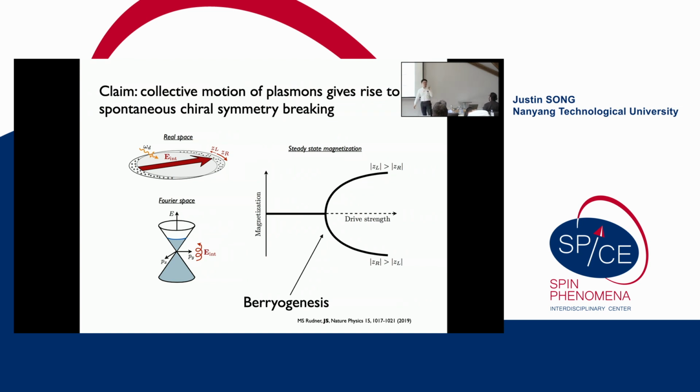The claim is, I take a disk, let's say, of metallic graphene, doped graphene, because I love plasmons, all right? I'm going to shine linearly polarized light, non-chiral, all right? And my claim is that if the amplitude of that linearly polarized light is large enough, I will start to develop spontaneously either left-hand or right-hand moving stuff. Here you see that the plasmons will spontaneously decide to move left-hand or right-hand. So this is a kind of intertwined phase now of light and matter.